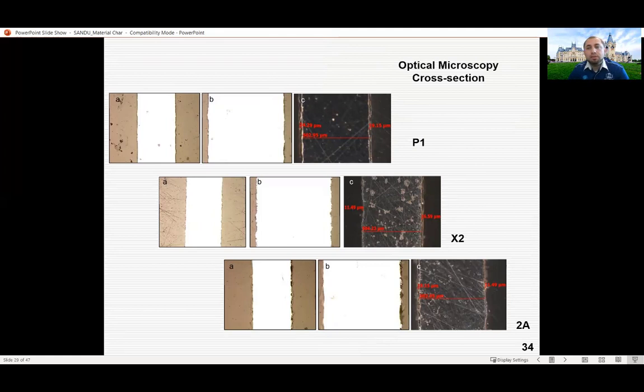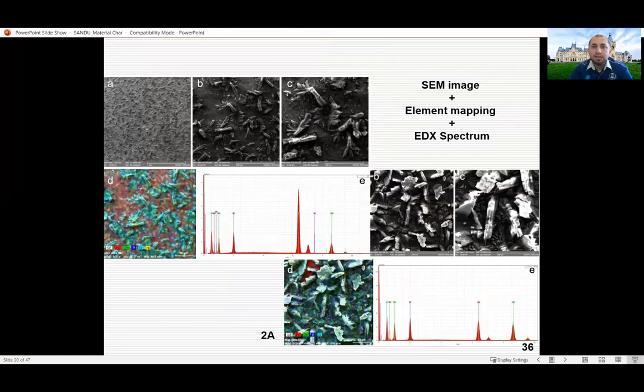These are some filters adapted to the optical microscopy in order to get what we need in there. Also, what was easy to identify in cross-section, we had steel sheets deposited with the phosphate layers, and we could measure them after we put them in the resin and sliced it in cross-section. We could measure exactly the thickness of the deposited layers. Here, as you can see, some examples. Also, some images of these types of phosphating. I obtained many types of phosphate coatings, some of them more compact, others not so compact. And here we have the surface topography, then the elemental mapping with iron, zinc, phosphorus, oxygen, and nickel.